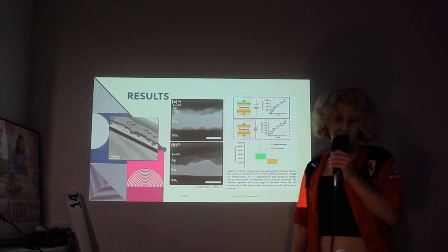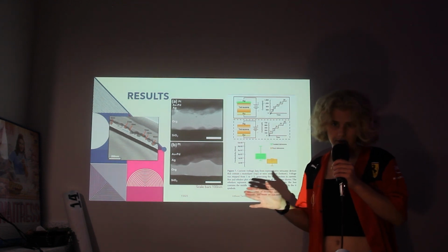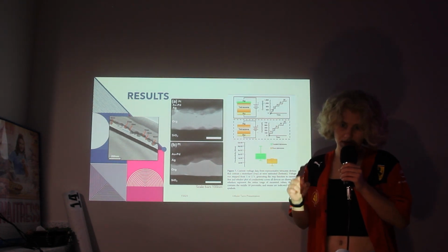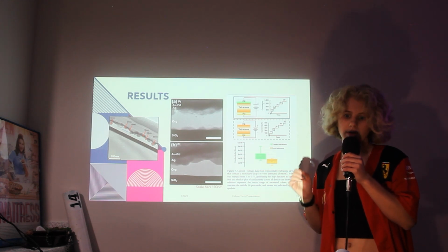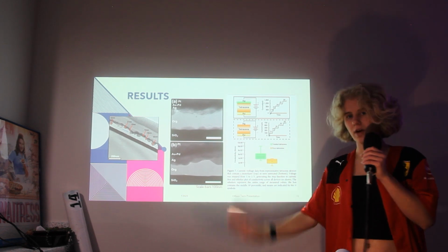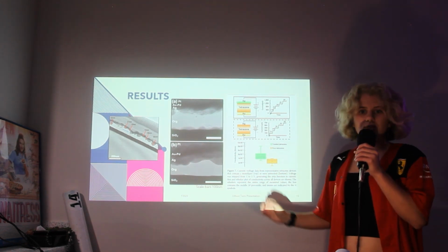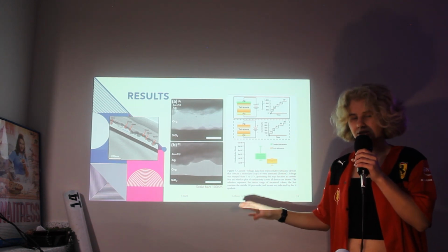The irregularity is more prevalent for perpendicular to surface tetracene compared to parallel to surface tetracene, since the upright conformation is less reactive to the Diels-Alder addition of the dienophiles, the functionalization of that layer. Although they have another paper on how defects in that layer do propagate the Diels-Alder reaction.